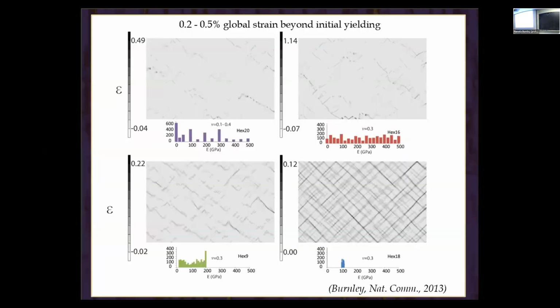So here are, in black and white now, all 4 models. So we can look at the variations in how the shear localization works. I have different global strains on the 4 models because I have a problem with the models crashing. At some point, when you have too many parallel plastic shear bands, then the computer can't decide which one is going to do all the shearing, and so it crashes.